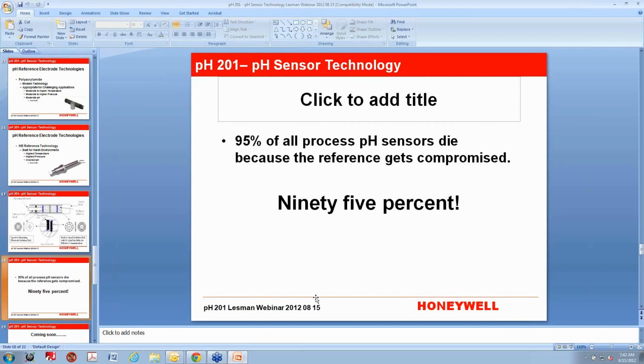But here's the deal. 95+% of all process pH sensors die because the reference gets compromised. 95% is a lot, which is why you don't see very different measuring electrode technologies, but you see a lot of different reference electrode technologies, because the weakness in pH sensors is the reference electrode. And so that's what manufacturers have gone after over time. And this HB technology is a patented technology.